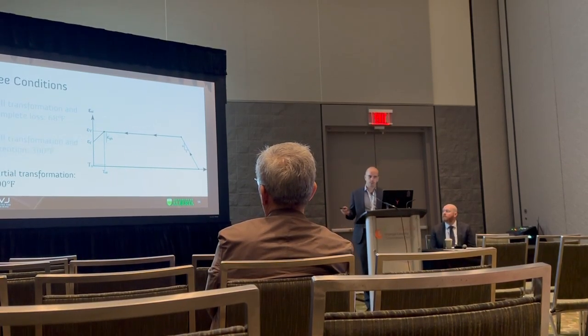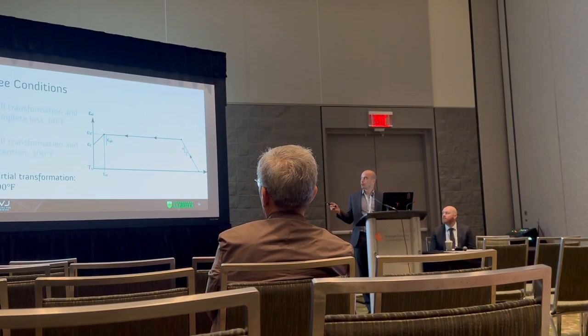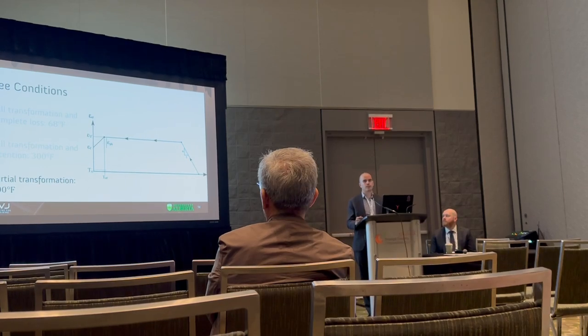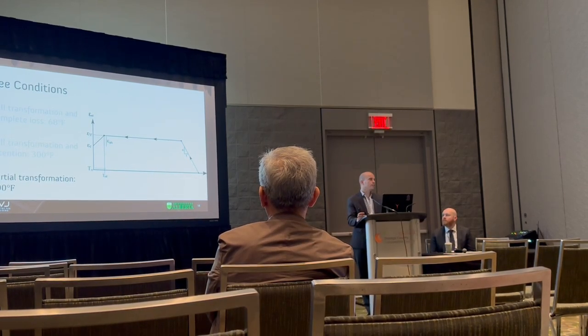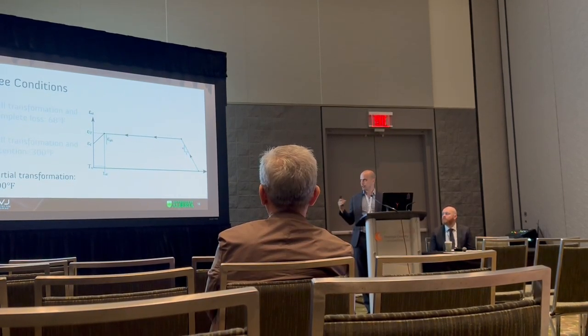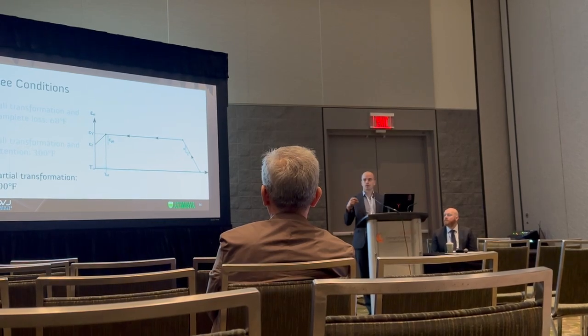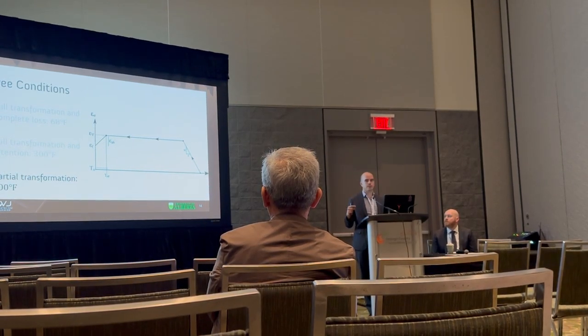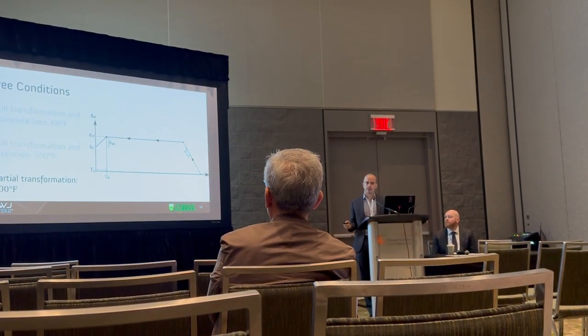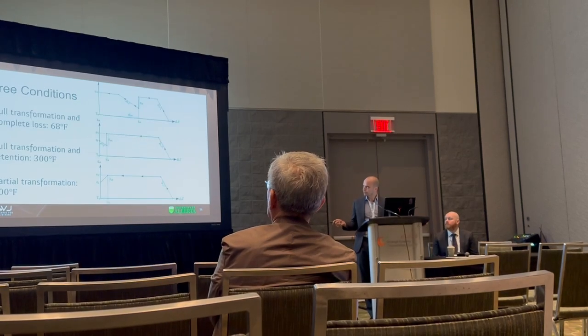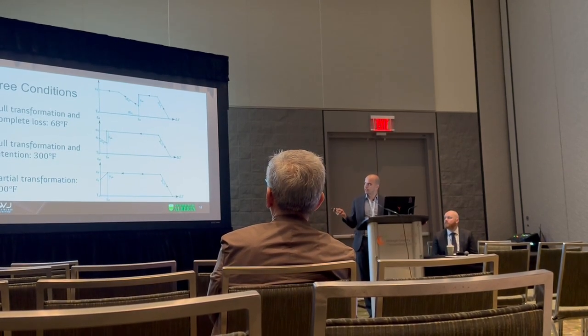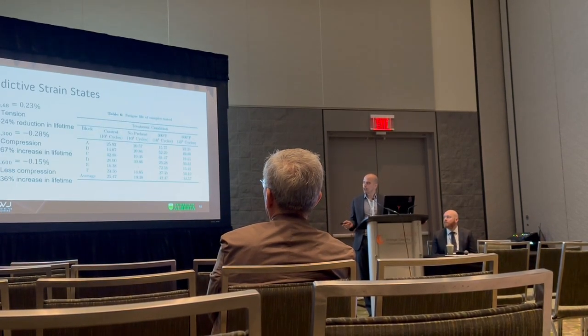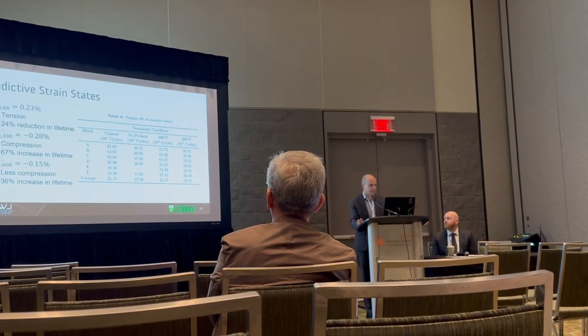And then at 600, we have to actually look at the transition. We're past the start of martensite formation, but we didn't hit the completion. So while it probably still proceeded to complete the martensite transformation, there was no strain developed because there was no thermal gradient. So that stress just gets absorbed. So there's our three conditions: 68, 300, 600. Now we're going to look at how it compares to that fatigue resistance we saw.